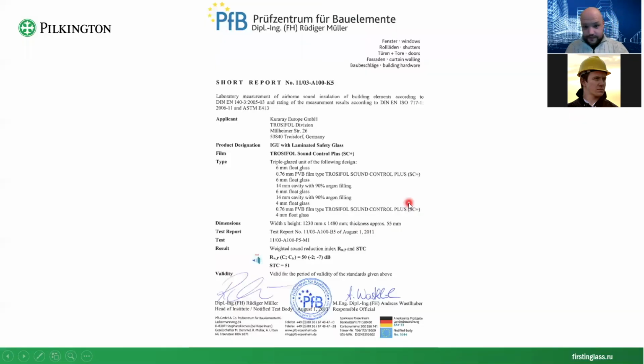What is the maximum, you may ask? This is a test report for a triple IGunit, with 2 times laminated glass, so 6 and 6 millimeter and 4 and 4. Already a much more sophisticated IGunit, and it has Rw of 50. Also see these coefficients, right? 50 decibel. If you increase the thickness of individual glass in the lamination, you can go up to where I would say maximum is 54. But that's about it. And it requires a very heavy, very big, and very expensive IGunit to make.